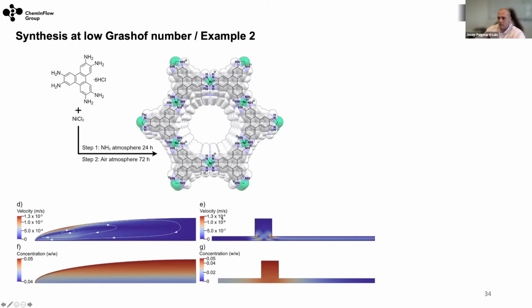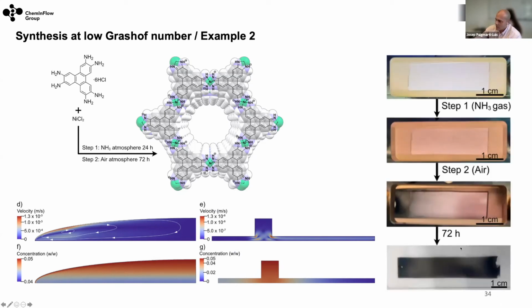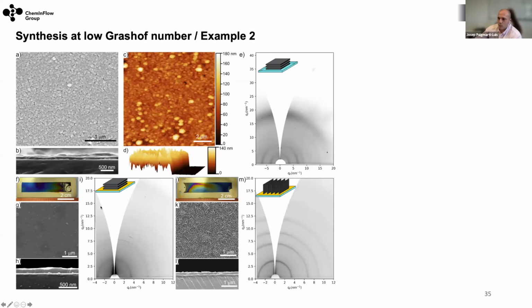So what you see is that the convection, if you look at the units, is reduced by 10,000 times. And then what happens is the contrary of what we had here. Here, the diffusion of the reagents goes in favor of gravity, whereas here it is perpendicular. So it's like you are simulating the microgravity condition that you have in the International Space Station. What we observe is that under these conditions we can achieve very long films, centimeter-long films of this 2D conductive MOF. Then, playing with the chemistry of the surface, we can have an alignment in favor of the surface, or we can grow the crystals perpendicular to the surface. So we can control the orientation of this 2D conductive MOF on the surface.